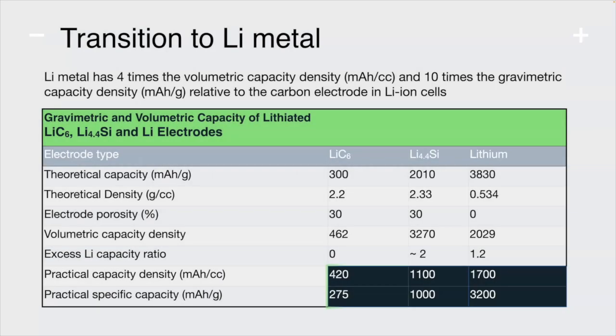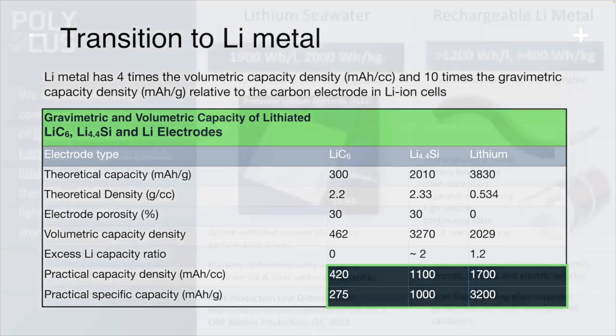But the push to solid state, in most cases, not all, but in many cases, involves a transition from carbon to silicon and then ultimately to lithium metal. And here's just a comparison of the gravimetric and volumetric capacity density of lithiated electrodes moving from carbon to silicon to lithium. In the black boxes at the bottom right, you can see that lithium is more than four times better volumetrically than carbon and more than 10 times on a weight basis. Everybody knows there is an incentive to move in this direction. You're going to have hopefully lighter, and safer or as safe batteries. So let's look at that.